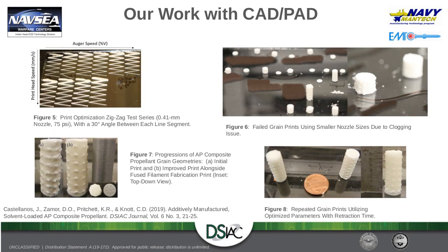Another thing is that ammonium perchlorate is highly hygroscopic, so it will agglomerate fairly quickly, at least to our standards. Even in choosing a solvent, some of these solvents are not 100% pure, so they'll also be hygroscopic to some respect, and a carrier of water will definitely help with the AP, or ammonium perchlorate, agglomeration, and that too will influence its printability. So those factors were looked at.